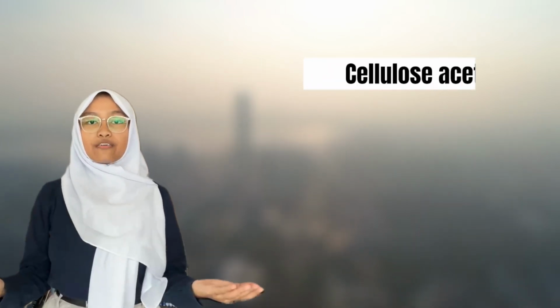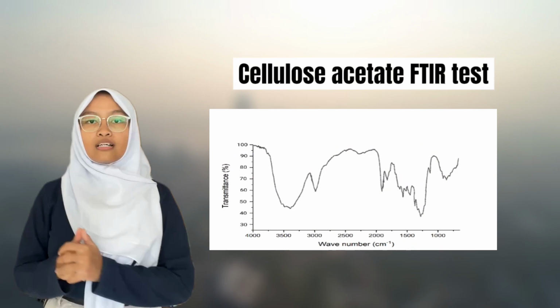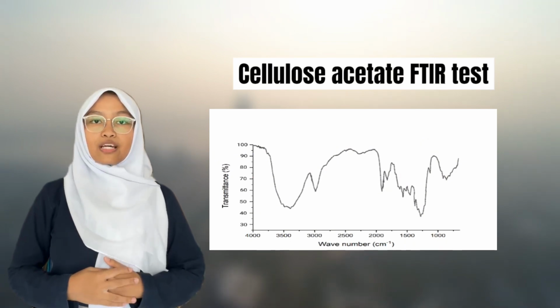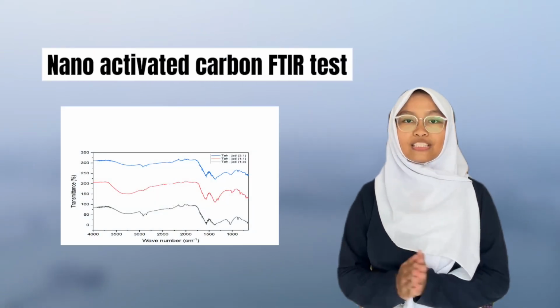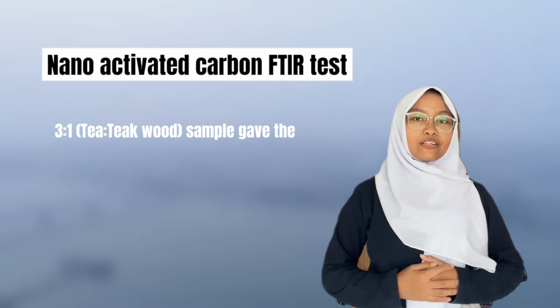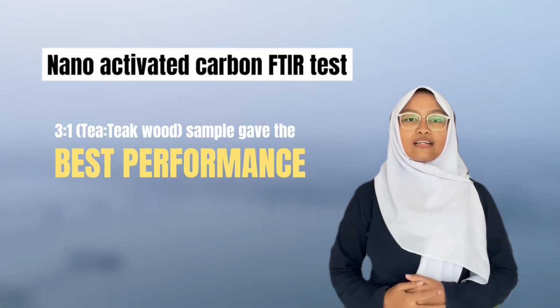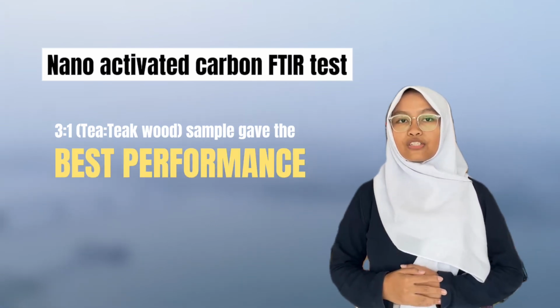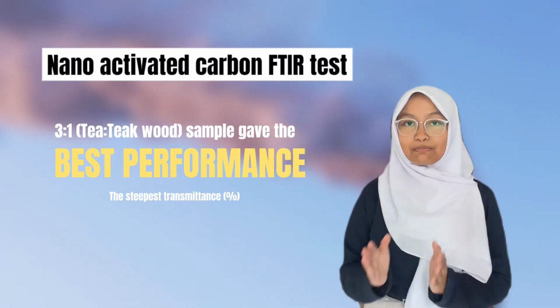The researcher conducted FTIR test on cellulose acetate produced from coconut grass. The FTIR result showed the presence of carbonyl groups, which proved that the acetylation process was successful. Next, FTIR was conducted on nano activated carbon composite made from tea and teak wood powder. The results showed that the sample with a 3:1 ratio of tea and teak wood powder gave the best performance.